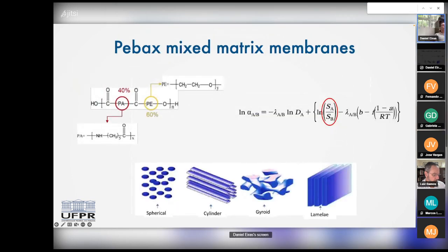Based on that idea, what I've been doing in my group is to develop what we call mixed matrix membranes. Mixed matrix membranes are materials that are formed by two different types of materials. I can use a polymer and a zeolite. I can use a polymer and a polymer with a different structure to form mixed matrix membranes. So one of the works I've been doing is with this material called PEBAX, that is a copolymer that combines a polyamide group, PA group, and a PEO group.